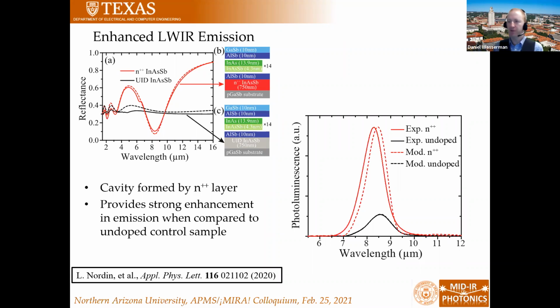In terms of the field confinement, you can get a significant enhancement of your fields. The problem is always that you need to get the light out, right? So there's this balancing act between having a very strong Purcell effect and then putting something into that system that outcouples the light. And that's the real balancing act.